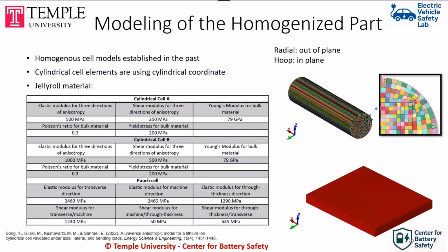So we have developed this for cylindrical cells and pouch cells. For cylindrical cells, it is very important to have the direction of the layers properly considered, because if you have a mesh like this, that's our cube element mesh, each of the elements will have different directions, and that will not be consistent with what we want. So again, Marian developed a tool for us to divide one part into parts, where each row of elements is a different part, and then they have coordinates that are aligned with the material direction.